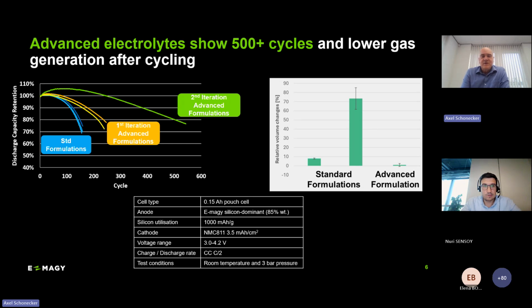The other challenge that everybody talks about is, of course, if you work with pure silicon, it's a limited lifetime, the cycle life that is achieved in batteries. And in this field, we are actually progressing very fast at the moment in cooperation with electrolyte partners. And we have tested a lot what we call standard formulations. That is just what you see in the blue lines in the graph here, where we typically achieve cycle lifetimes in battery of around 200 cycles maximum. These are the electrolytes that are developed for graphite and graphite anode material in combination, for example, with NMC cathodes, and they are limited.